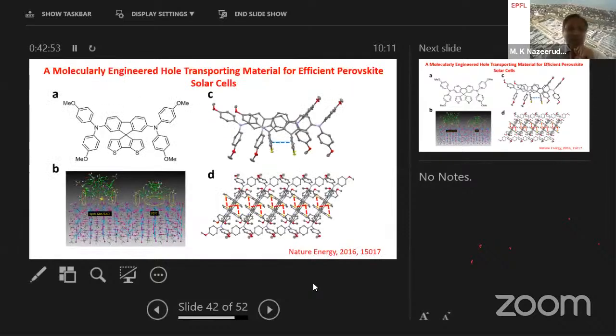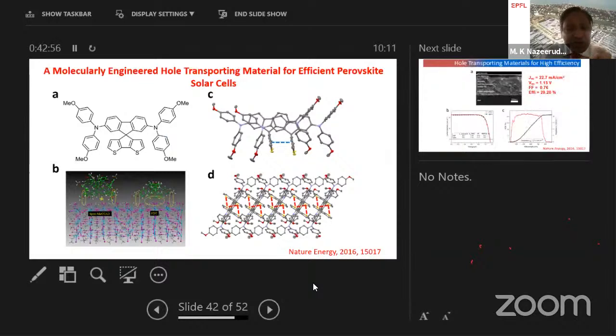Yes. Okay. Thank you. So this is a new hole transporting material which we developed and published in 2016. And here we have a thiophene. The purpose of showing this molecule is, can we enhance the interaction between the hole transporting material and the perovskite layer? On the B panel, these are calculations done by Professor Filippo De Angelis, and the calculations clearly show an enhanced interaction between the perovskite and thiophene groups. Using this type of hole transporting material, we obtained over 20% efficiency.